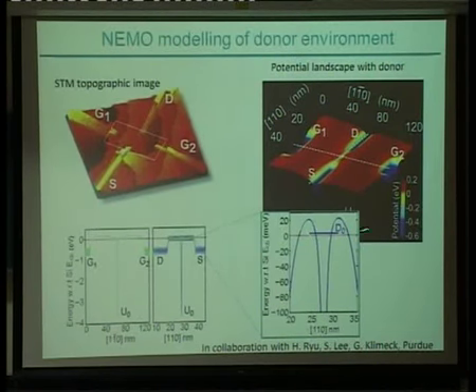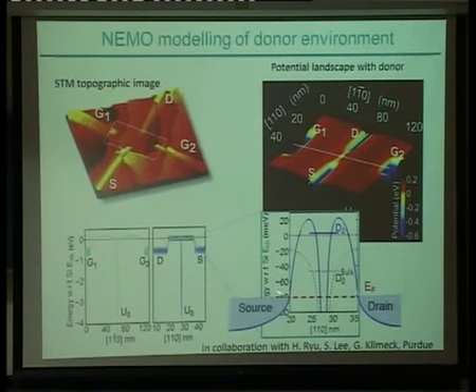And one of the key things you see is the D0 state here. This is the state at which the electron in the donor is actually sitting up here above the silicon conduction band. And that contrasts strongly with what you expect for a bulk-like phosphorus donor in silicon, where it's sitting 45 meV below the silicon conduction band.